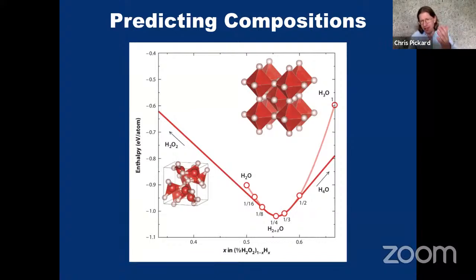So I won't go into this in great detail, but the long and the short of it is you compute what's known as a Maxwell construction or convex hull, which is a graphical construction which tells you which compositions are stable to decomposition to neighboring compositions. So compositions on the convex hull are stable to decomposition to other compositions. Points off the convex hull, in the case here H2O in the middle of the plot, it's above the convex hull, therefore it will decompose into this hydrogen-rich phase, so H2 plus delta O, and hydrogen peroxide, which is far to the left-hand side. Now take a look at the H3O structure. We published this H3O structure, and you'll see this structure again a bit later on, connected to sulfur hydride, which was the first big breakthrough in the superconducting hydrides experimentally.